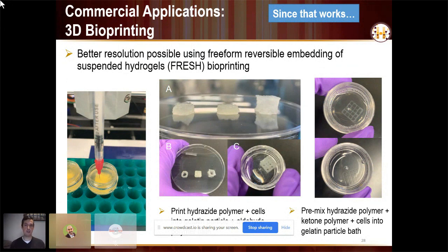You can see that we've been able to do this successfully using two approaches. One is where we have the hydrazide polymer and cells inside the needle, and then we print those into the mixture of the gelatin particles and our aldehyde polymers. So in this case, the cross-linking happens as the aldehyde polymer diffuses into the printed hydrazide solution, which is sort of held in place by the gelatin particles for long enough for that cross-linking to happen. Again, you see a little bit of anisotropic swelling here, which we're trying to address, but it does work to build fairly high and maintained structure hydrogels that are printed.